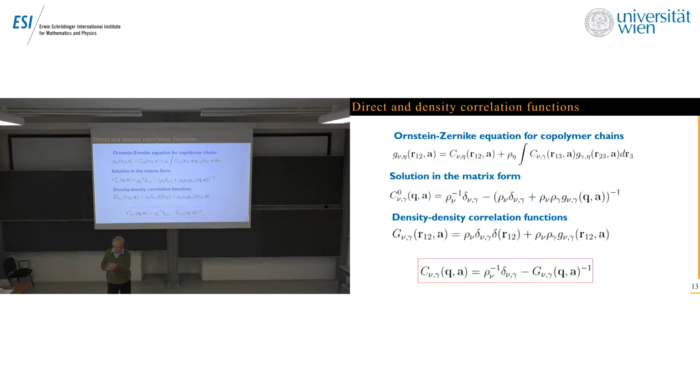Then in other terms, of course, there is a deviation, but this reproduces exactly the spinodal line compared to the formal expansion. But in Leibler's theory, again, the higher order correlation functions, even in the theory of polymers, cannot be calculated exactly. So there are other approximations which are used. So this looks reasonable.